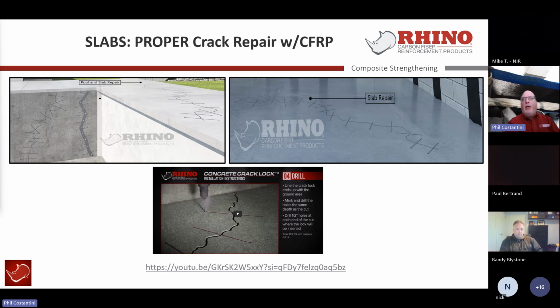The nice thing about the crack lock is that it was designed and engineered to handle fairly significant cracking on top of slabs. I wouldn't really use it as a repair for wall cracks. I like our crack lock repair with our 4-inch or 6-inch wide unidirectional weave. But for on top of slab applications where someone wants to put down a coating, I highly recommend it in industrial warehousing, or, let's say, a garage that's got really bad cracking in it. But when you start seeing heaves or potential shifting in a slab, that's going to be a whole different methodology, and for all intents and purposes, I would shy away from utilizing crack lock for that. But for anything from 1/16 of an inch to 1/4 of an inch, up to at least just under a full inch crack, you can utilize these.